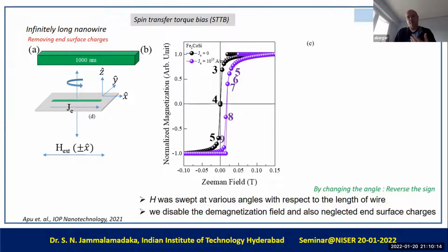Then I'm not surprised you get the bias, but of course, I think you cannot really realize that, because if you send a current through this wire, it has a certain spin polarization, depending on the spin polarization of your electrons at the Fermi surface. However, once the magnetization switches, the spin current switches too, and that's not in your calculation, right? Yeah, that's not in our calculation. Okay. All right, I think now I understand that. So we try to explain this phenomenon using the domain wall resistance, as I have mentioned, using the non-adiabatic spin transport term.